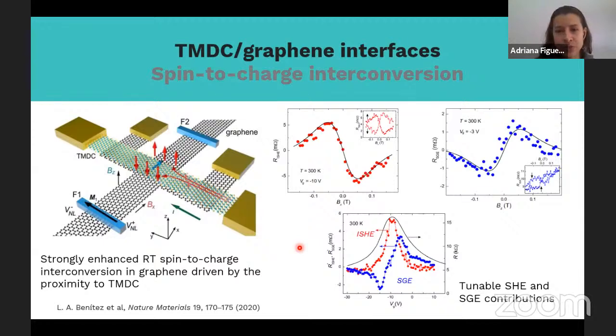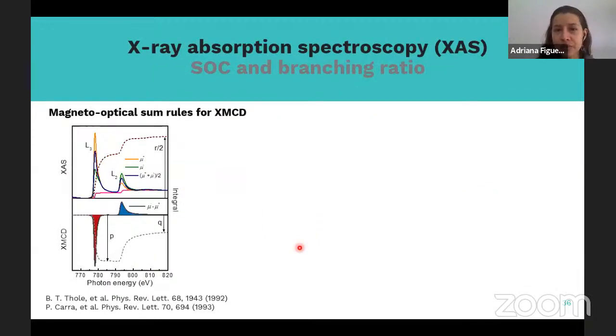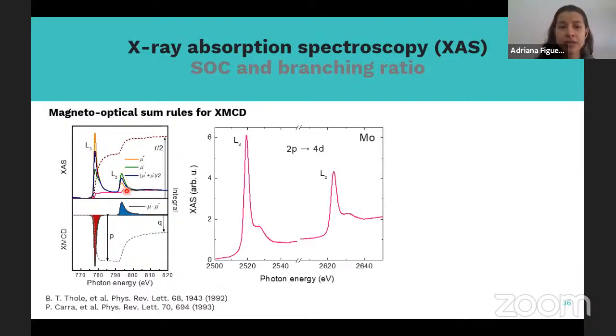What I wanted to show you today is that using X-ray absorption spectroscopy, you have a way to observe such spin-orbit coupling in these graphene TMD layers, by analysis of the X-ray absorption spectra. As I showed you in the first part of my talk, if we use magneto-optical sum rules for XMCD, we are able to extract the magnetic moments of an element that we are probing. But if we go one step back, if we analyze just the X-ray absorption spectra,